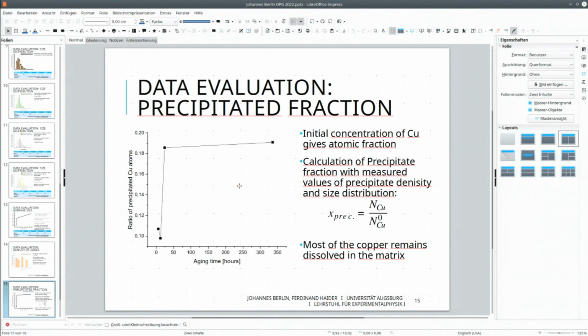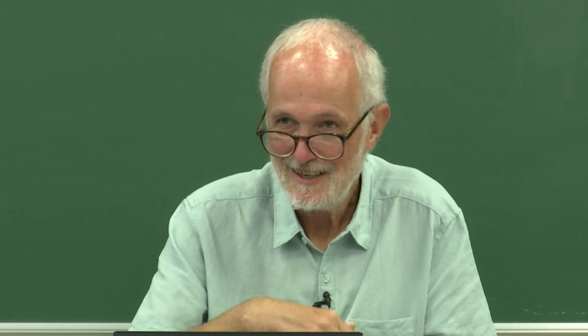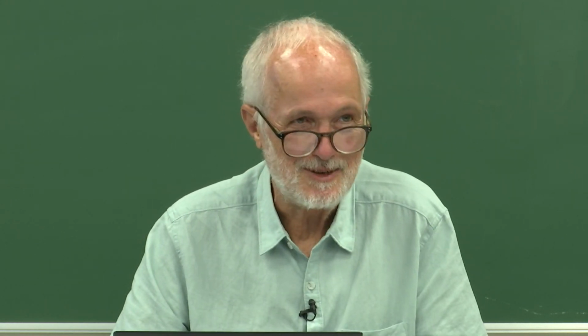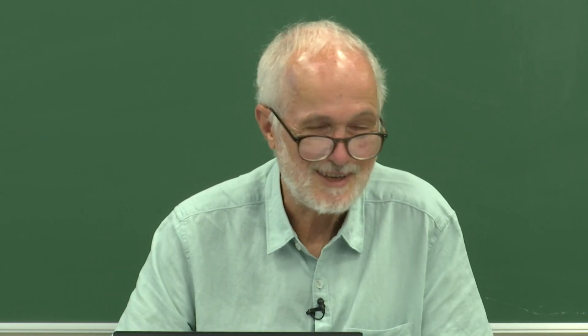At this time we did not have this nice microscope, but I told them it's much more costly to do electron microscopy than DSC. In calorimetry, you can trace the dissolution of precipitates. So we offered to do that, and it turned out there was indeed a change in microstructure during these 10 years or so.